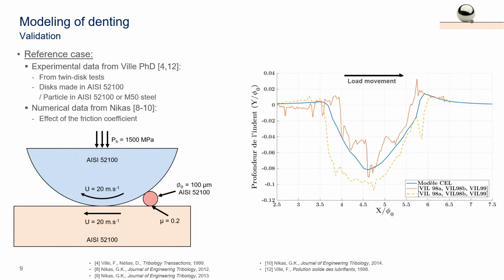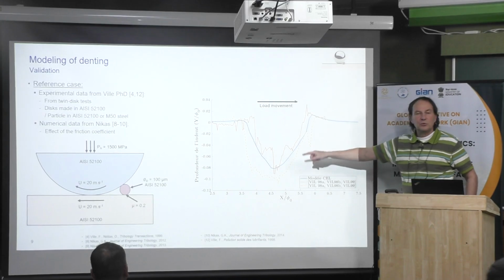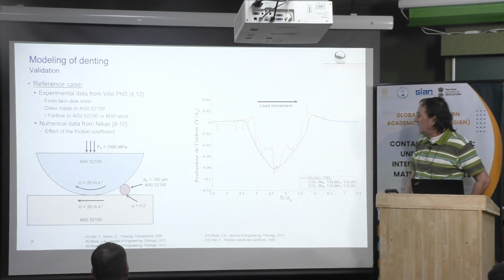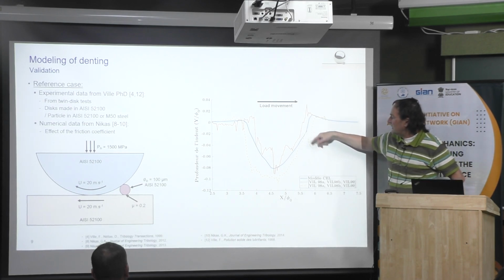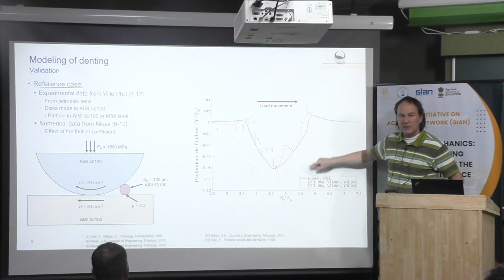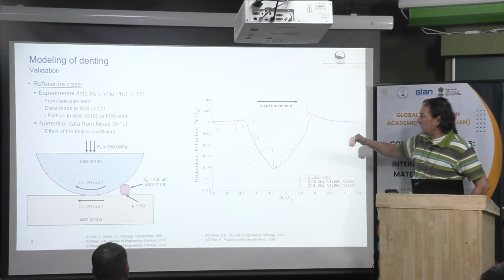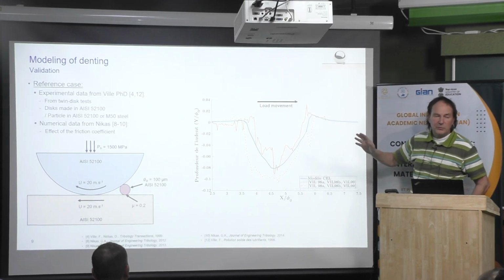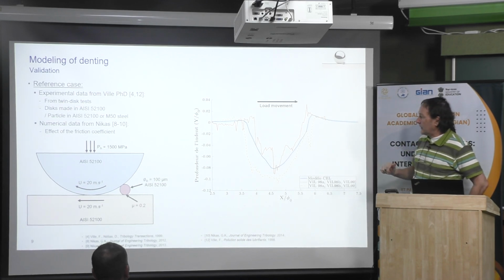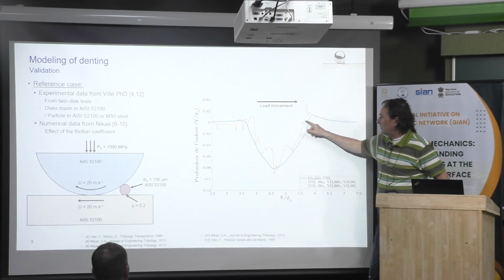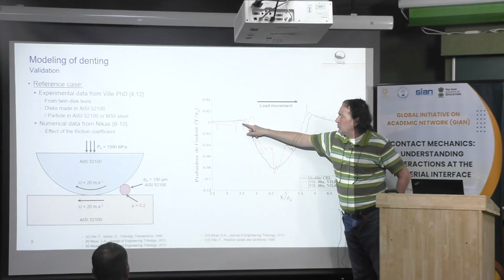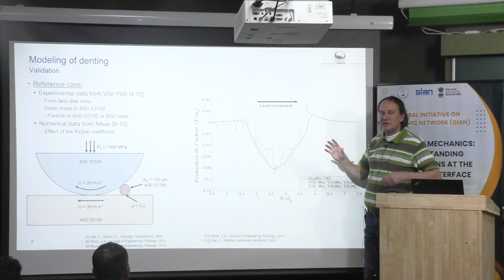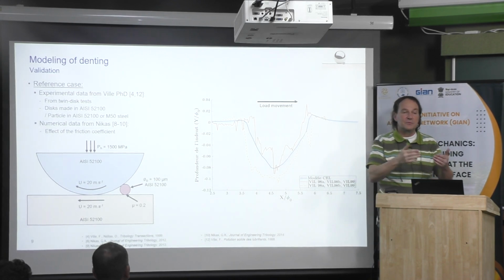Then this is a comparison between the result of the model. The blue curve corresponds to the simulation, and the red and the yellow one correspond to experiments. First, you can see there is a good agreement, roughly, because it's difficult to have exactly the same parameters. And second, you can see that the shoulder is not axisymmetric. The shoulder here is smaller than here. Okay, then there is some effect of the rolling.